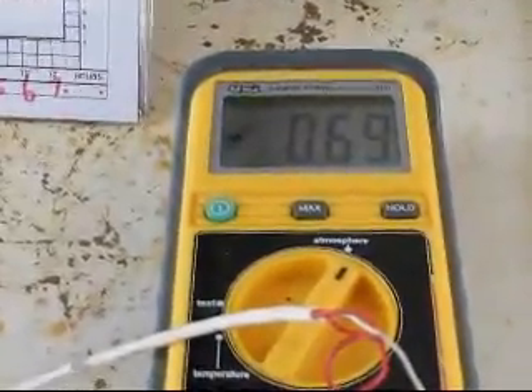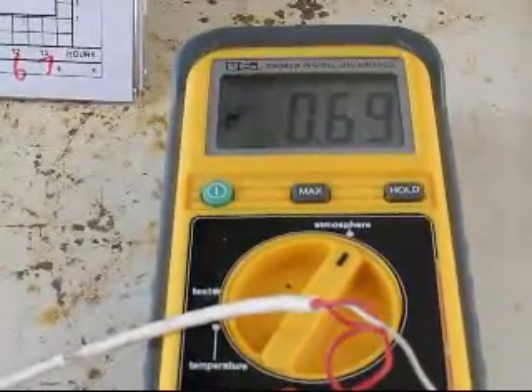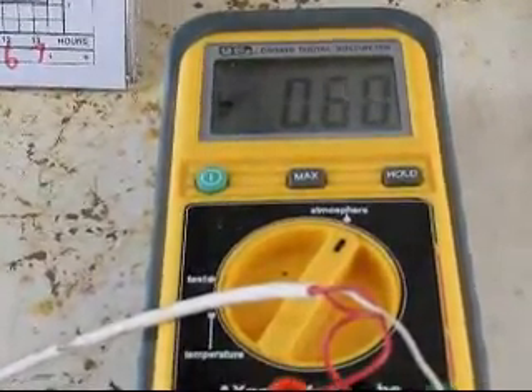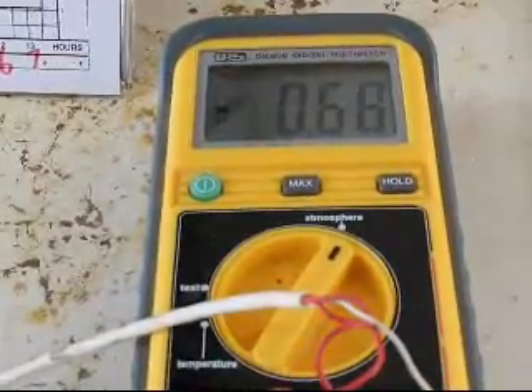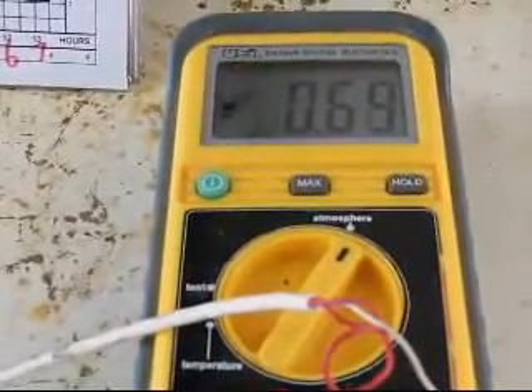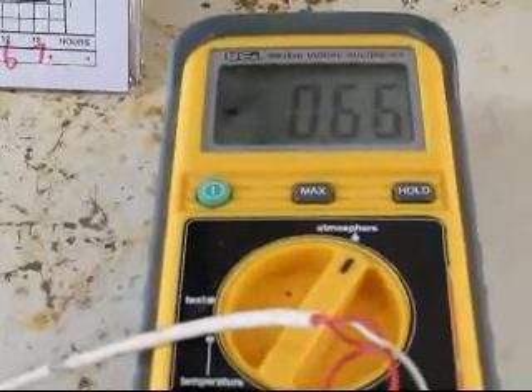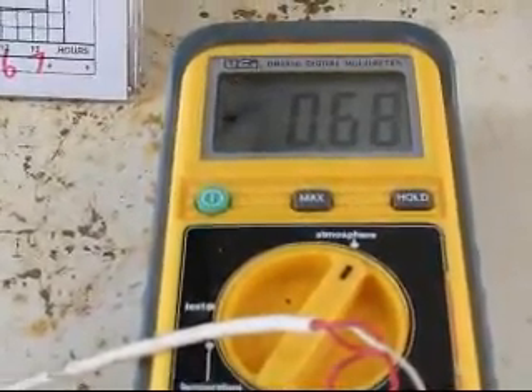Okay, I closed the damper about 1 inch, and you'll notice that there is a lot of KO wool packing there. It is critically important to close up the air holes around the damper. If air gets in here, then it acts like a super damper, and it is very inefficient. Okay, so closing the damper approximately 1 inch put the kiln into very nice reduction. So 0.6 is good reduction, and so we're exactly where we want to be. So we can just leave it here probably for the rest of the firing.